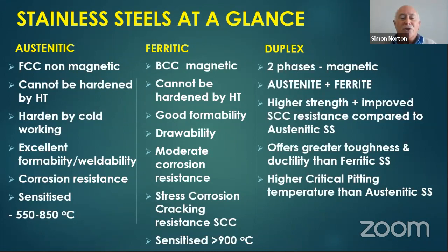And then, of course, there are the DUPLEX stainless steels. And I would like to emphasize to those listening, start to look at the DUPLEX stainless steels. They are enormously useful materials. For the same thickness of austenitic 304, 316, you could use a DUPLEX stainless steel at a much lower thickness and achieve far better performance out of DUPLEX stainless steel.